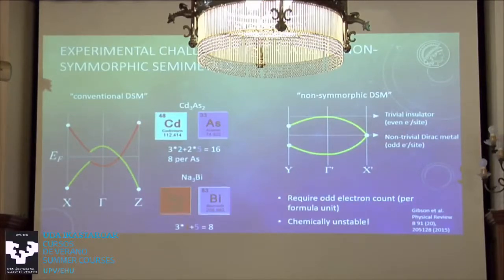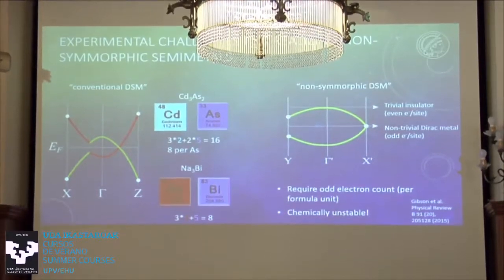But the problem is that when we looked at the conventional 3D Dirac semimetals here, like cadmium arsenide or sodium bismuth, those were charge balanced materials. And they're charge balanced and the Fermi level is still here where we want it to be. But non-symmorphic materials are different because we folded the band structure. Now, if we do the chemistry rule of charge balance, where we don't count per unit cell, we count per formula unit, then when the chemist says charge balance, the Fermi level is always up here, where it's trivial and nobody cares about it.